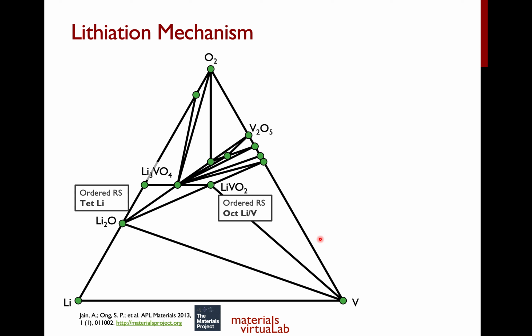Now I'm going to go to my favorite tool for understanding the thermodynamics of lithium intercalation, which is the phase diagram. What you see on this slide is the lithium vanadium oxygen phase diagram that I downloaded from the Materials Project. This is the database of all the known materials with all the computed energies, and we can construct this phase diagram from the 0K DFT energies.